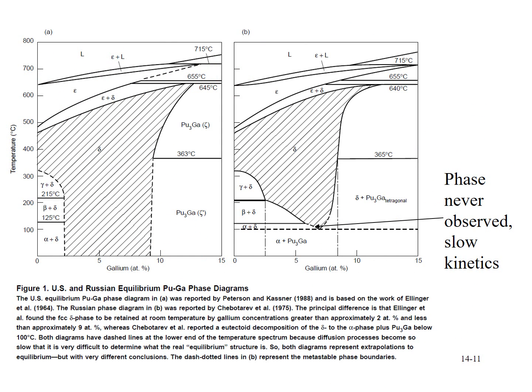Some details of the gallium-plutonium phase diagram are shown here at the low gallium concentration end, and these are the US and Russian phase diagrams. The information is shown here. The main difference is that the Russians observed a complicated intermetallic, plutonium alpha phase plus this plutonium-gallium intermetallic, under conditions where the US phase diagram just predicted a single delta phase.